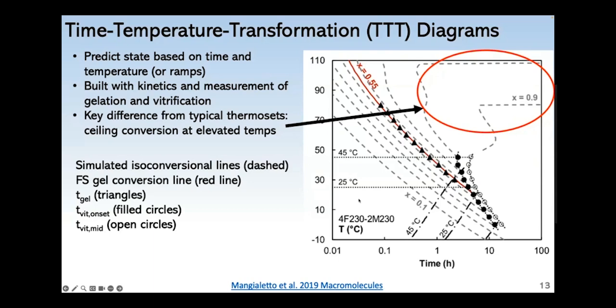To explain this a little bit, on the y-axis would be temperature and the x-axis time, and the dashed lines are the conversion. The Flory-Stockmayer gel conversion is the red line shown. So for example, with this particular chemistry, if you isothermed at 45 C and tracked along, it would take about an hour in order for it to gel. And the key difference that I wanted to point out from a conventional thermoset is that at high temperature, the equilibrium conversion levels off. And even though they don't show it, the same thing would be true for the gel conversion. It would eventually be the equilibrium conversion.